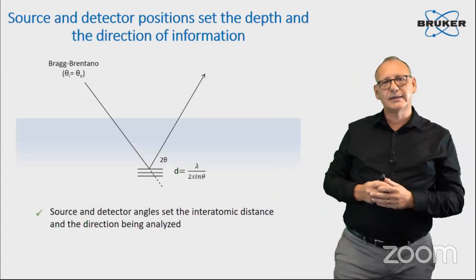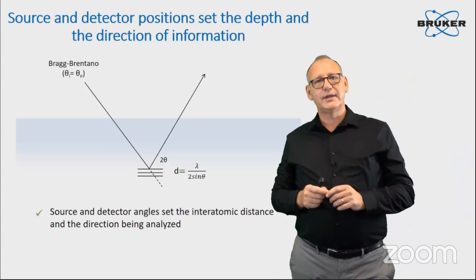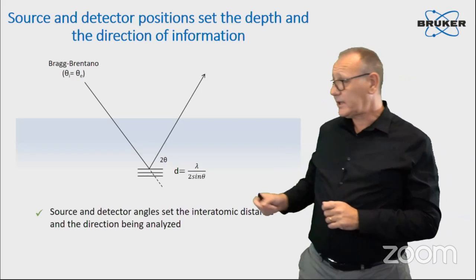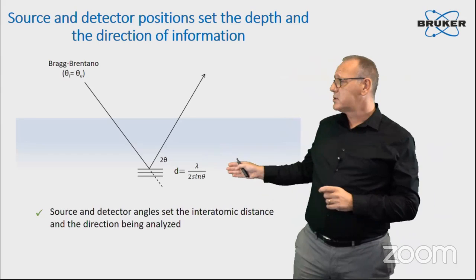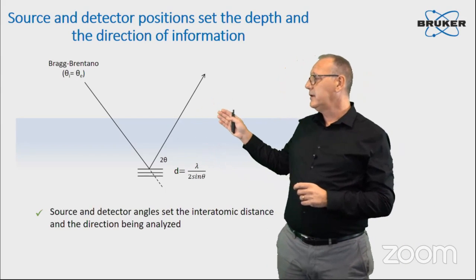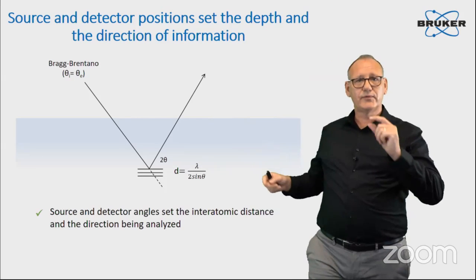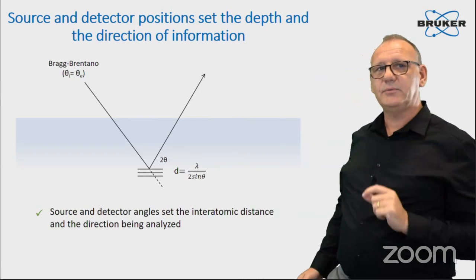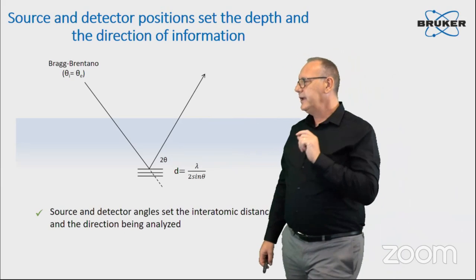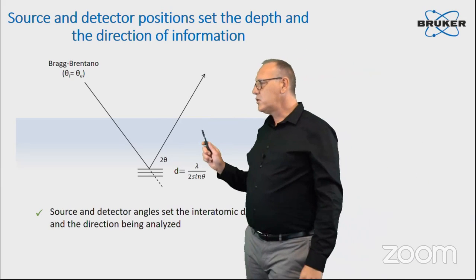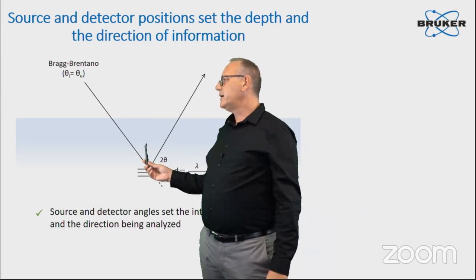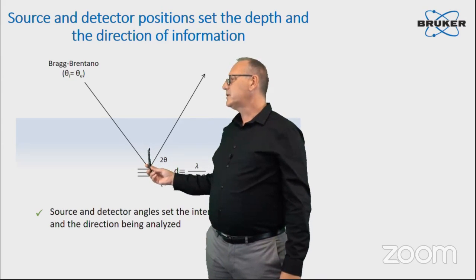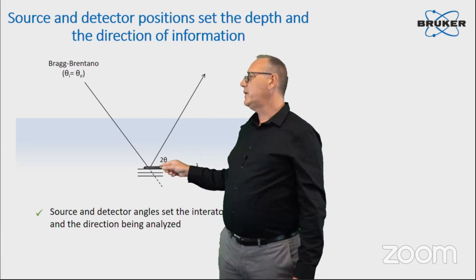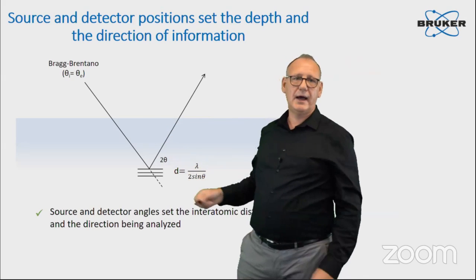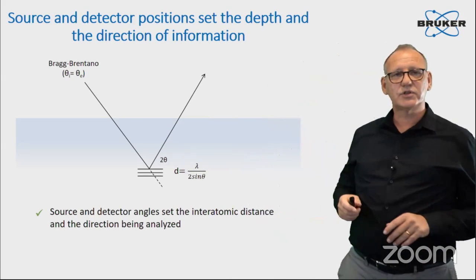What we've heard is that, first of all, the source and the detector angle set the interatomic distance. This is nothing but Bragg's law. So at a given incident angle, exit angle, this fixes the 2 theta, and you will be able to observe a certain d value. But what is even more important is that it doesn't only set the interatomic distance, but it also sets the direction being analyzed. So this would be the diffraction vector. And this means that in symmetric diffraction, only the planes which are parallel to the surface will be analyzed. And this will not change during the measurement.